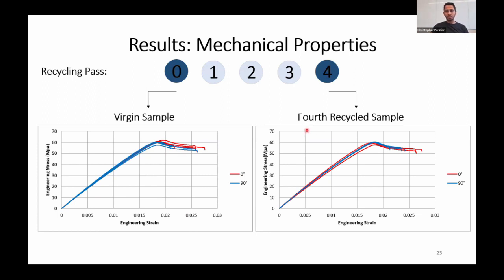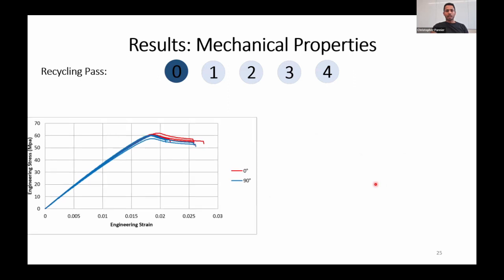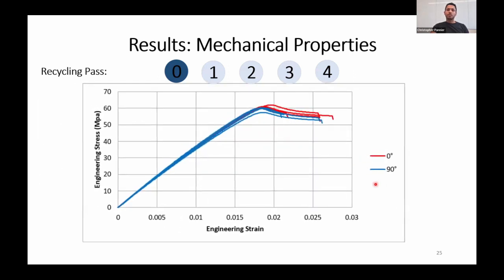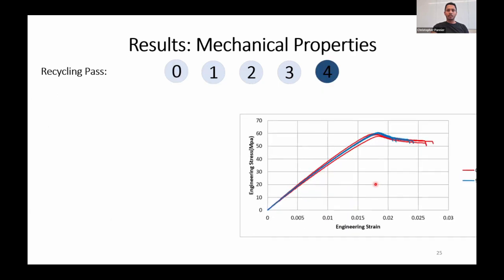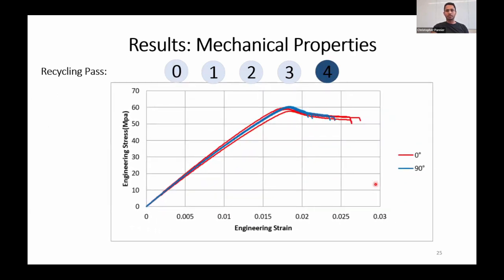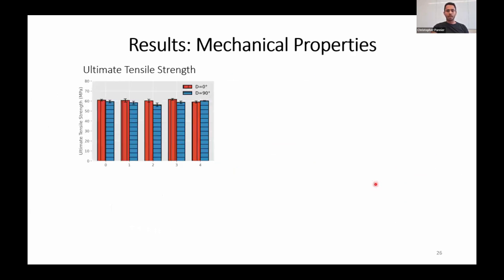One thing to mention is that when we went to the fourth recycle pass, we noticed that the 0 degree is a little bit tougher than the 90 degree, but that's the only thing we noticed from this experiment. I'm just showing here the zero recycled again, and this is the fourth recycled for our process.